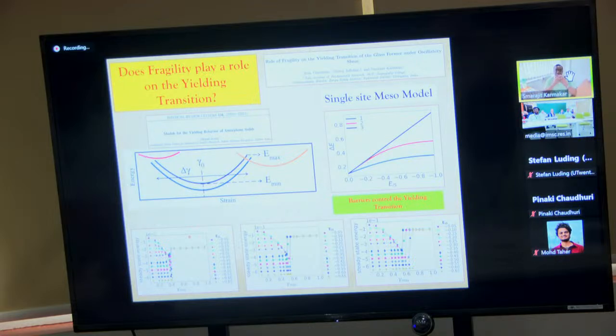But what was missing in this was the difference that one might get if you take a fragile versus a strong glass forming liquid. And what we feel is that the answer lies in how the energy barrier changes in these two types of liquids when you generate glasses from them. For example, for strong liquids it has been shown by explicit calculations that the typical energy barrier does not change with cooling history. It changes when you are in the poorly annealed regime, but when you go to the well annealed glass regime, it is more or less saturated. This is represented by this blue curve. And if you have very fragile glasses, then the energy barrier grows strongly with your annealing protocol or your temperature.